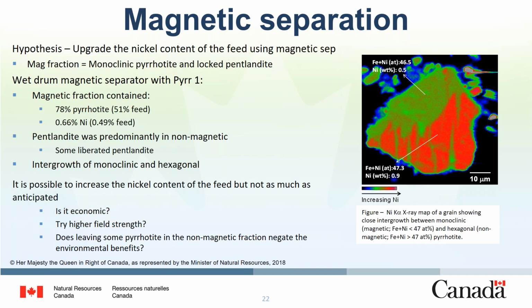In addition, the nickel preferentially partitioned in the non-mag hexagonal form, which is non-magnetic. The close intergrowth between the pyrrhotite forms and the preferential partitioning of nickel are shown in this nickel X-ray map of pyrrhotite grain shown on your screen. At this point, we're not sure if magnetic separation improves the overall process economics. There is also a question if leaving some of the pyrrhotite in the non-mag fraction negates some of the environmental benefits, so this has to be further studied.